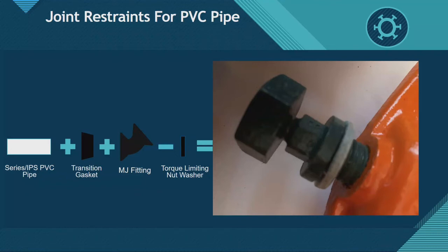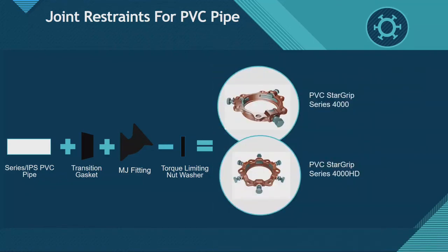The reason is that washer prevents the wedges from engaging too far into a PVC C900 pipe. On an IPS pipe, you need those wedges to go in further. If you don't remove that washer, wedges won't engage the pipe. They may not even engage the pipe at all. But if they do touch the pipe, they're not touching the pipe enough to get the reaction on the pipe to restrain it. So that's a very important thing to make sure you remove that.